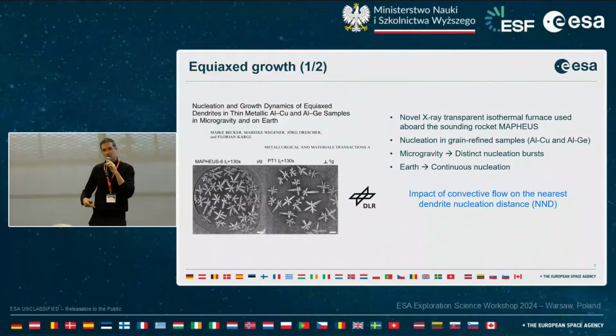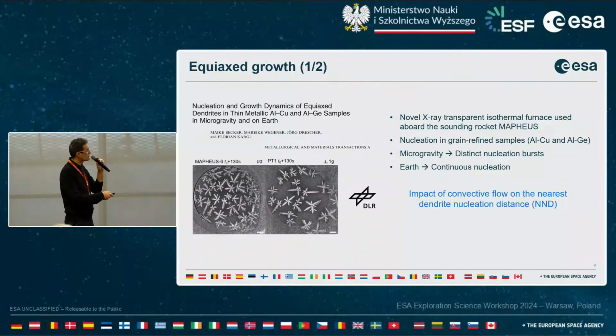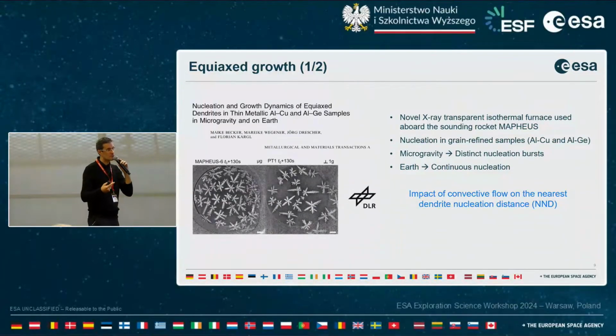It is again an illustration that convective flow has a significant impact on the solidification, and the need for microgravity experiments, because this convective flow impacts the so-called nearest nucleation distance, which would be the distance between a grain and the observation of new grains, because convective flow modifies the solute field around the dendrites and thus impacts the nucleation process.